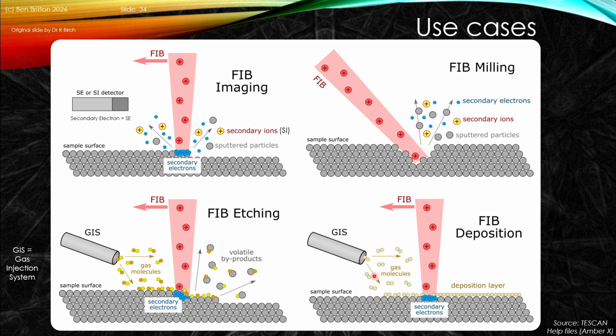Slightly differently, we can switch the gas that's in the GIS system, and we can now effectively float a series of gas molecules, and those gas molecules will float around on the surface. A few of them will adsorb on the surface of our object, and then interact with the primary incident ions as well as the secondary electrons, and you can get effectively a breakdown of those gas molecules to deposit them on the surface. And this is, for instance, where we deposit a platinum-rich layer through the organic precursor breaking down on the surface of our object. Again, we'll see a bit later in the lectures how we can optimize the FIB for these different operational modes.